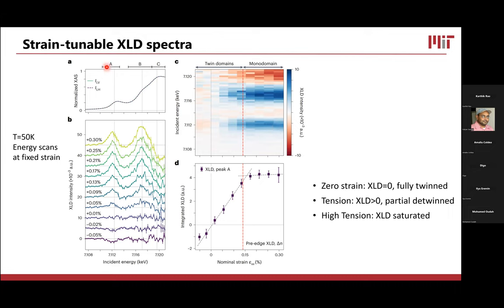Now, if you see this bracket here, if we sum up the intensity underneath this peak by using a fixed energy range, then we can define these points here. These points are the total intensity in this range as a function of strain. I should mention again that we're below the nematic transition, but we're not all the way down. Under compression, we see that the total value of the XLD for peak A is negative. Again, it increases very linearly with applied tension, and then it saturates. This saturation behavior is really important, because it's going to tell us about how the orbitals are connected to the lattice. The orbital susceptibility is connected to the lattice.